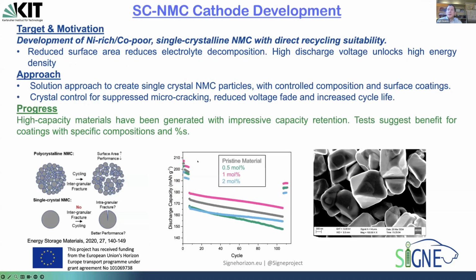On the cathode side, it's been led by KIT. These are our single crystal NMC materials that you see down here. Again, with cobalt poor, so it's around 4% of cobalt content. And what they're really focused on, again, because these are aqueous processed, is they want to do surface coatings to allow for increased stability of those.